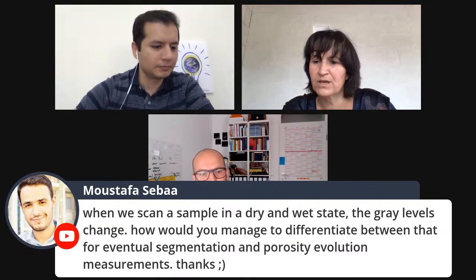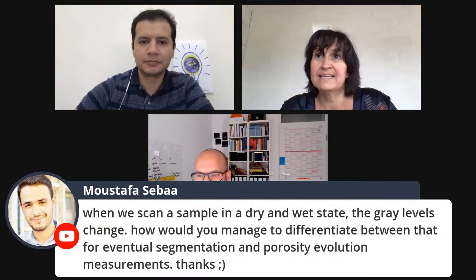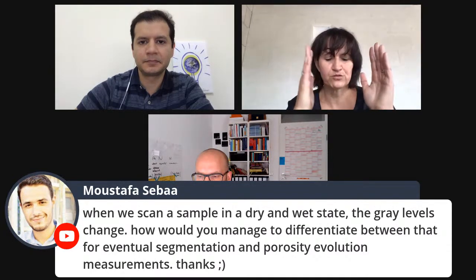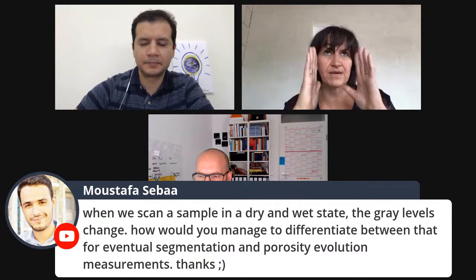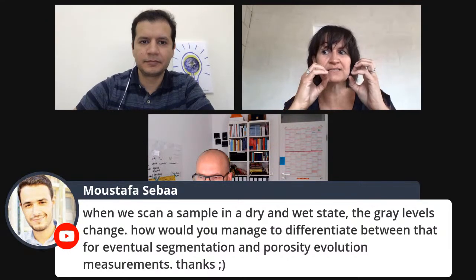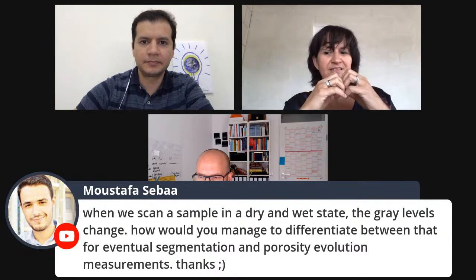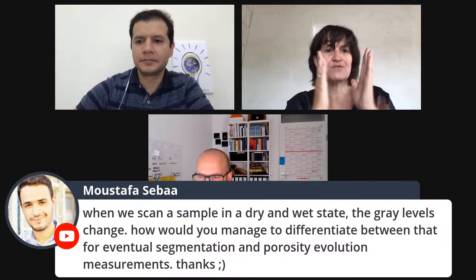Okay, then it depends if your wet sample and the matrix of your grains remain at the same place. So it depends on the material that you're scanning. For instance, if we have rocks where the grains remain stationary, even if they are wet or dry, what we do is differential imaging: we subtract and we see where you have the liquid, and that is what we use then for segmentation or, for instance, to study porosity.